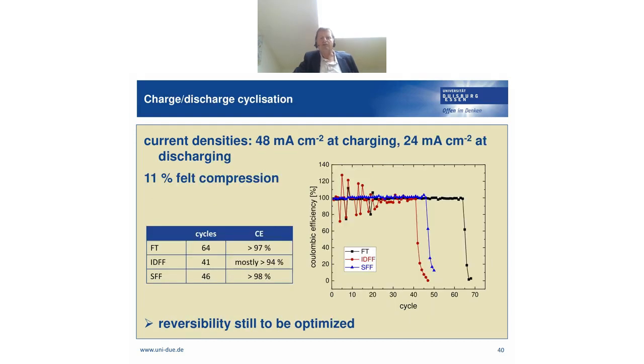We did some cycling, charging with almost 50 milliamps per square centimeter, and discharging was a little bit reduced, with half the current density. For the three flow field designs here, flow-through, interdigitated, and serpentine. And the best results, this is more than 60 cycles, could be obtained for the flow-through design of the flow field at the anode.